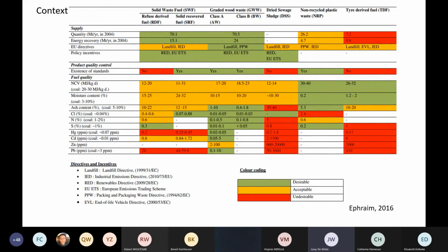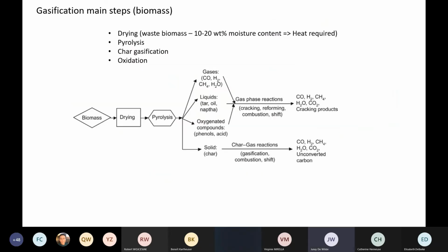There are some disadvantages, however, and that is mainly that there is more chlorine in it that you will have to deal with, and that will require either a pre-treatment or post-treatment. The same goes for a little bit of sulfur here, but still within acceptable limits. But it's mainly chlorine that is a problem. So we are focusing on gasification, and let me show you here what the main steps are in gasification.